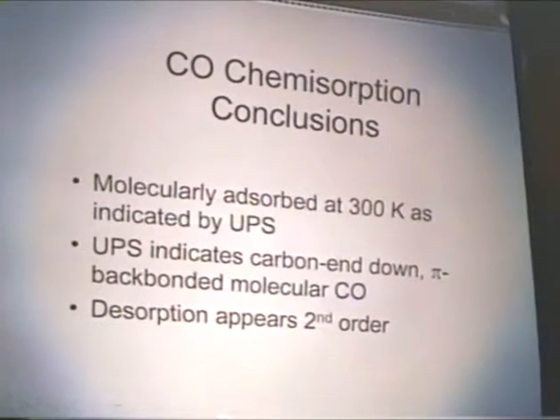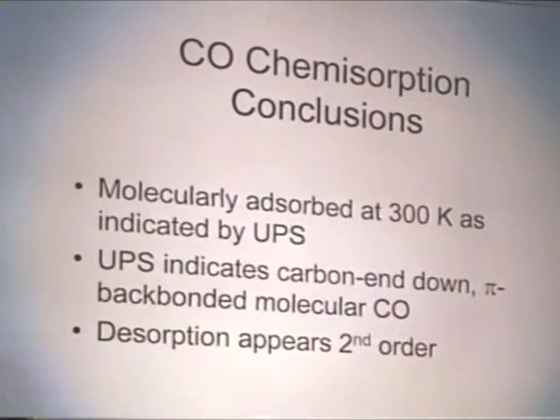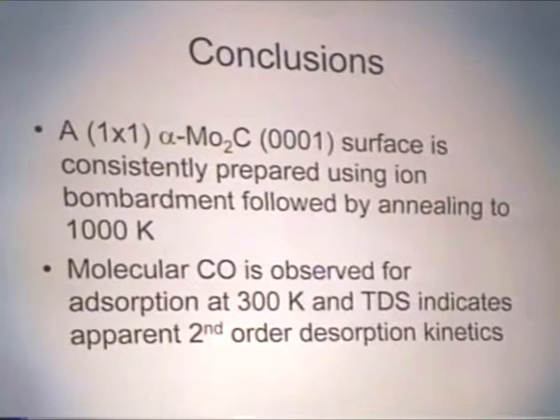Conclusions about our CO chemisorption. We have molecularly adsorbed CO at 300 Kelvin. We have a carbon-end down, pi-backbonded molecular CO on the surface, and the desorption appears second order. We are able to consistently prepare a one-by-one alpha molycarbide surface by ion bombarding and following that with annealing to 1,000 Kelvin. And we observe molecular CO adsorption at 300 Kelvin with apparent second-order desorption kinetics.